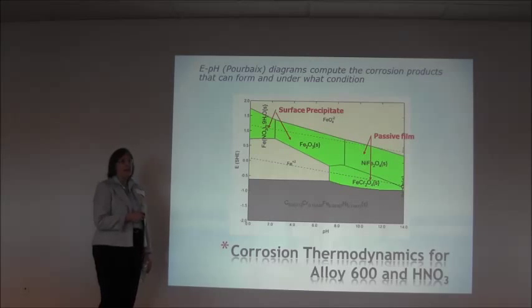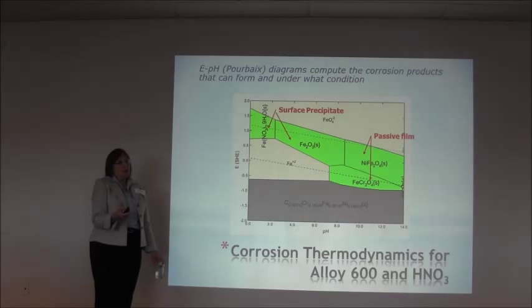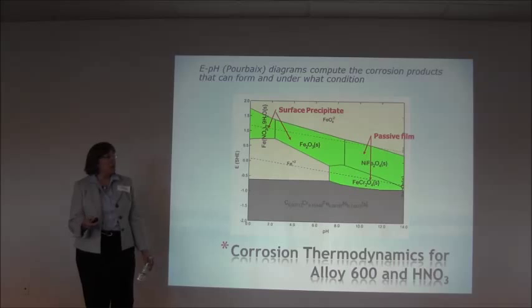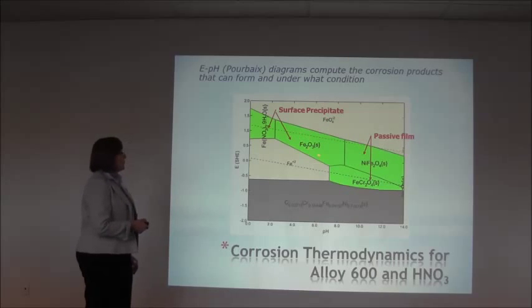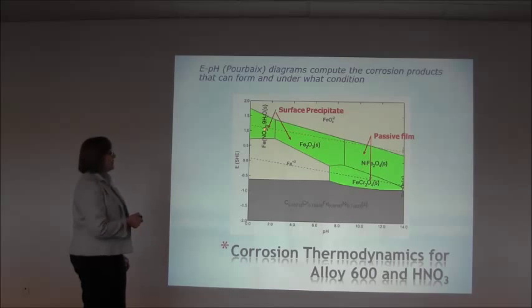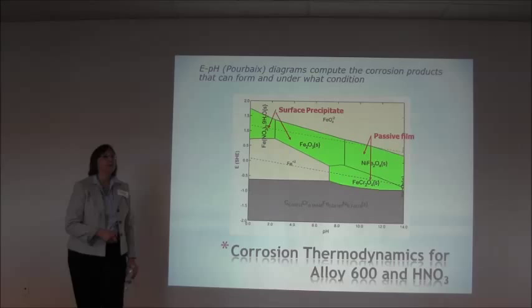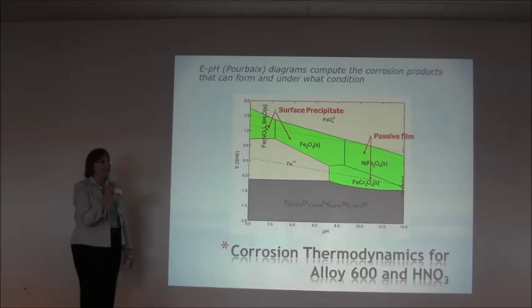A little bit of scale is good. I think Vince said a little bit of scale protects your pipe. It's not the best coating, but it's not the worst coating, right? So the green areas are going to be passivating films, the white areas are going to be corrosive films, and the gray areas are going to be inert. That's a way to boil down what Pourbaix did, and what OLI adds to it is the ion-ion interactions. And that's what we call the thermodynamics of corrosion.